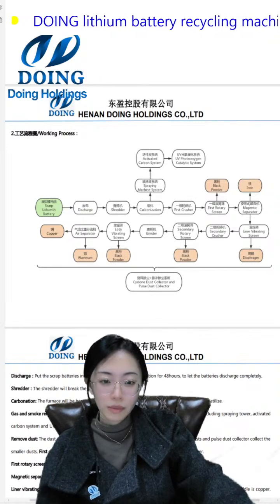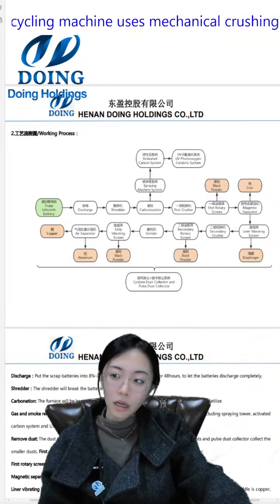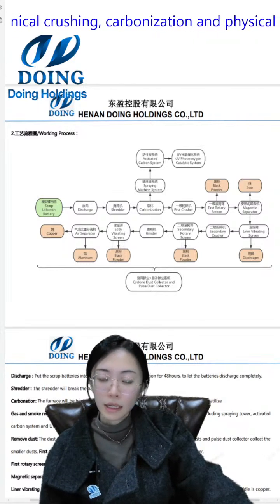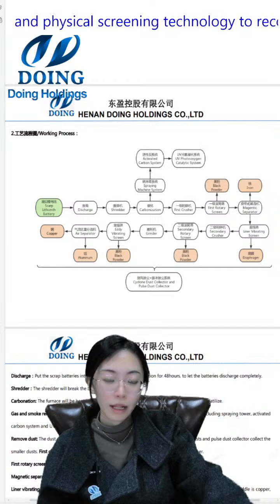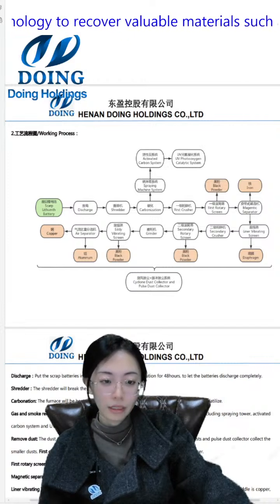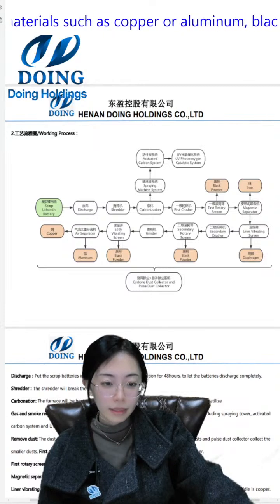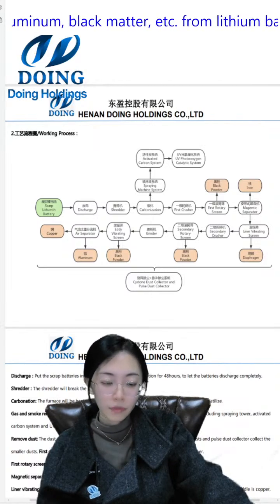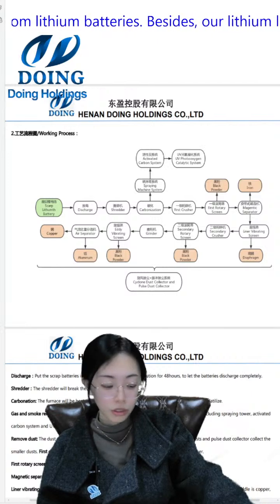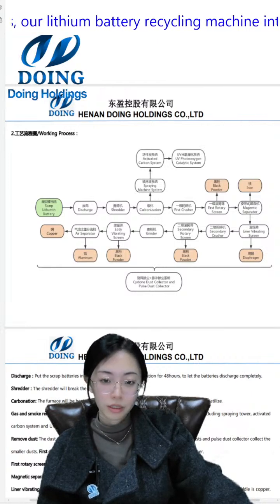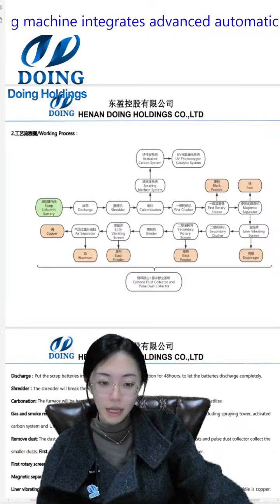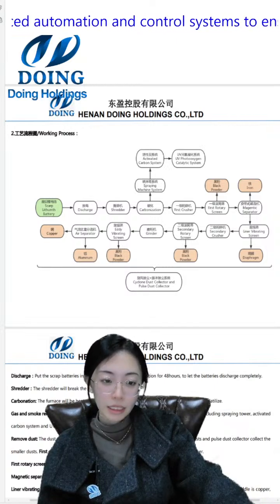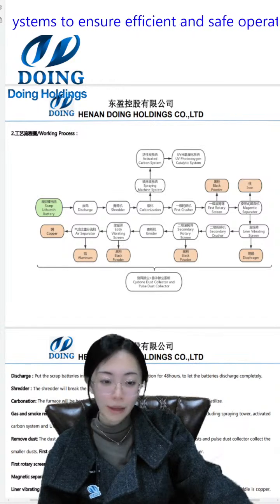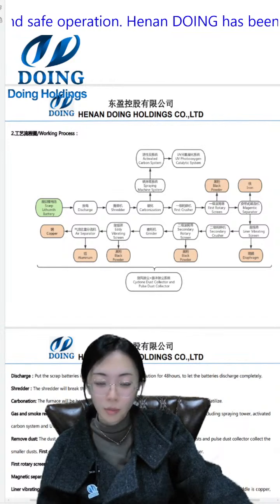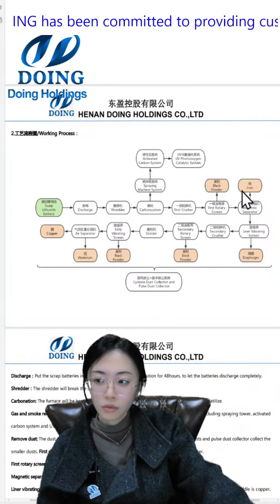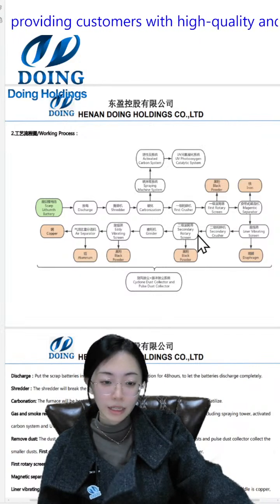It goes into it by using this sealed wind conveyor, and inside we have a 120 mesh screen to screen the black powder, the black powder that has reached the standard size. In this step, we will collect about 60 to 70% of the black powder, and other raw materials like the copper and aluminium will go into the next processing line.